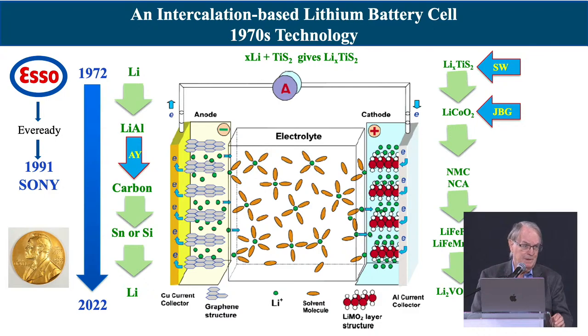So John Goodenough investigated lithium cobalt dioxide, which he was looking at as a magnetic material. He read our paper and said, this will work. He tried it and it did work. But any self-respecting chemist never tried it. We didn't try it. Our colleagues at Bell Labs didn't try it because we were all taught cobalt 4 doesn't exist. There's no point in even trying to pull the lithium out and make cobalt 4. So we learned, don't always believe what the textbooks say. And really in this whole area of batteries, most of these materials are thermodynamically metastable at some point.